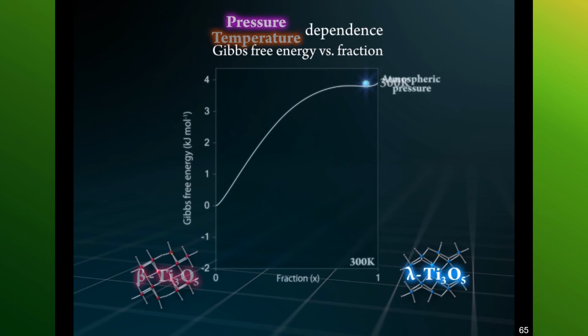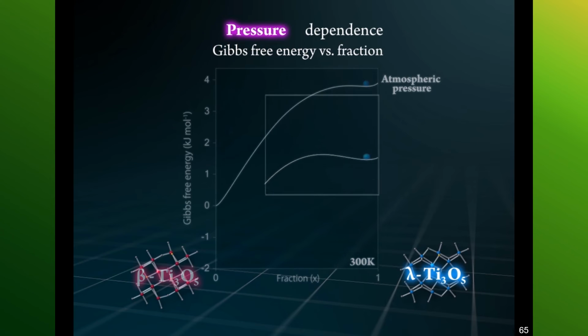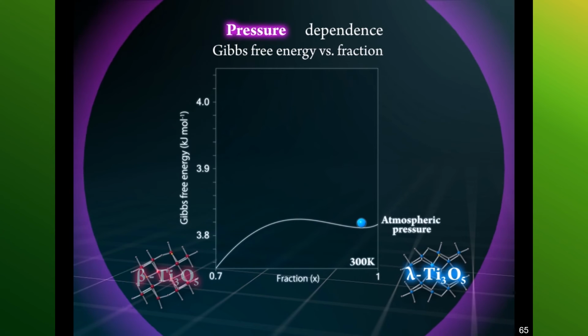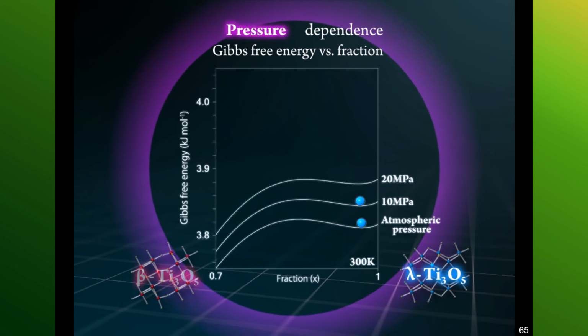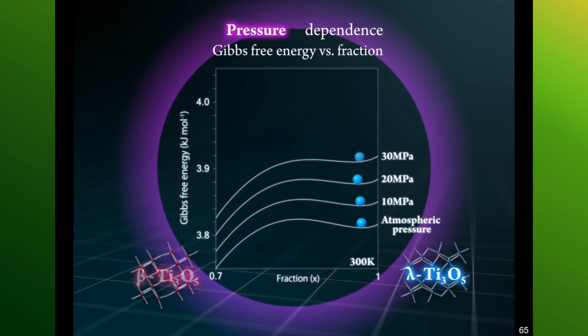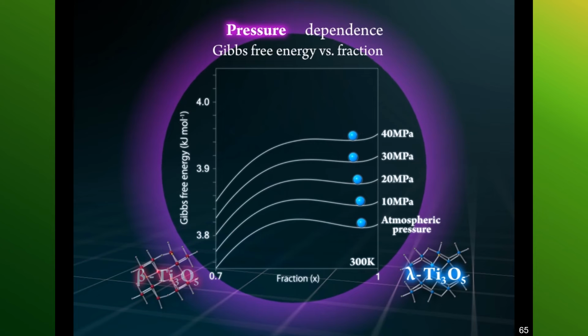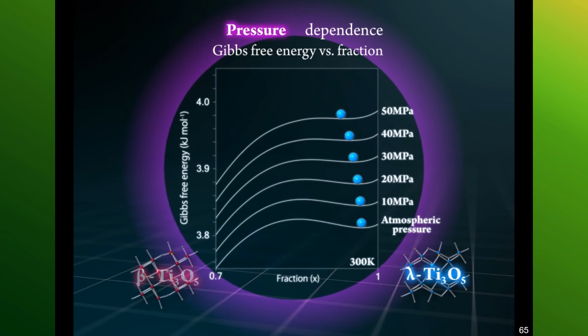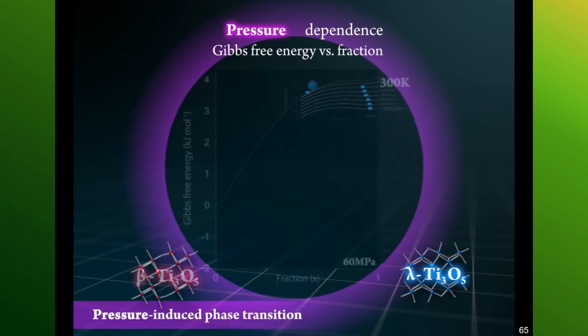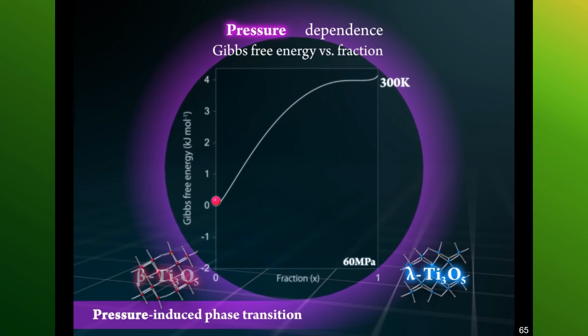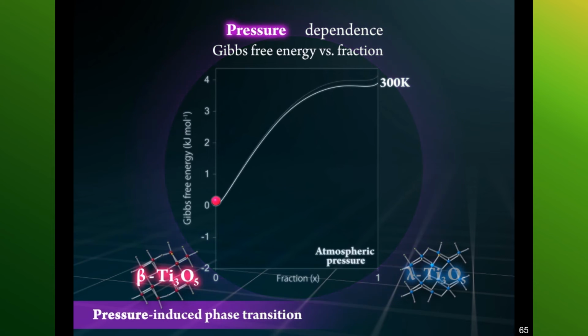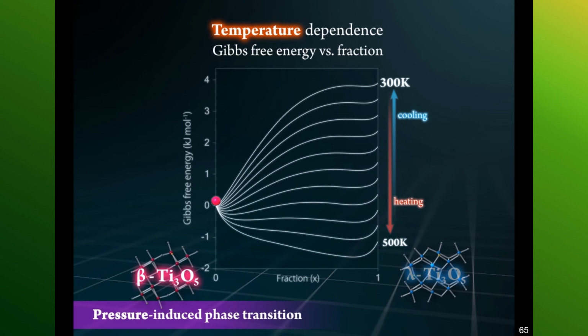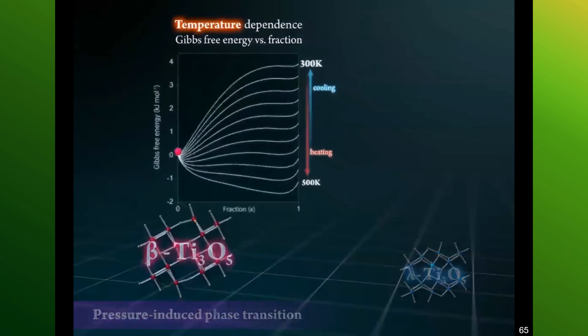Here, we focus on the Gibbs free energy curve at 300 Kelvin and take a look at the effect of external pressure. By the application of pressure, the Gibbs free energy curve gradually changes, and at 60 megapascal, the energy barrier disappears, causing the phase transition from lambda to beta phase, shown with the red ball. When the pressure is released, the energy barrier reappears, but beta phase is maintained since it is energetically stable.